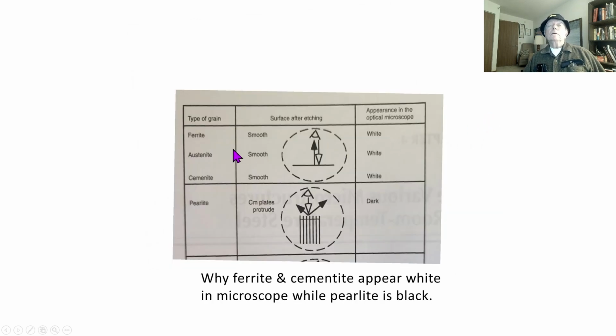This is a bit more info on that. Here are the 4 ites. Ferrite, austenite, and cementite are all phases. They're all crystalline materials, and they all etch smooth, and they're all white. Here's pearlite. It's a phase mixture. Black regions are cementite plates, and the white between them is ferrite. Well, ferrite etches much faster than cementite.